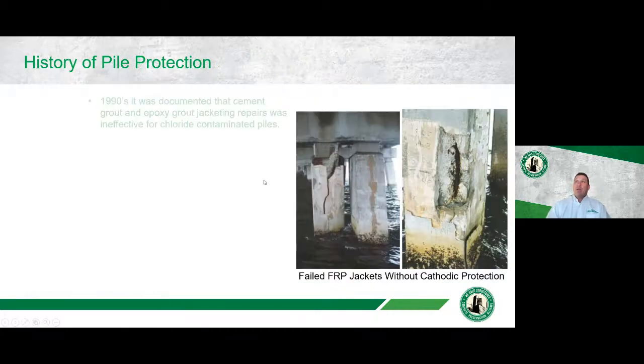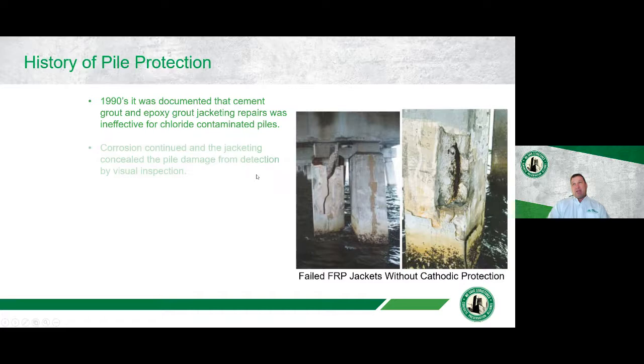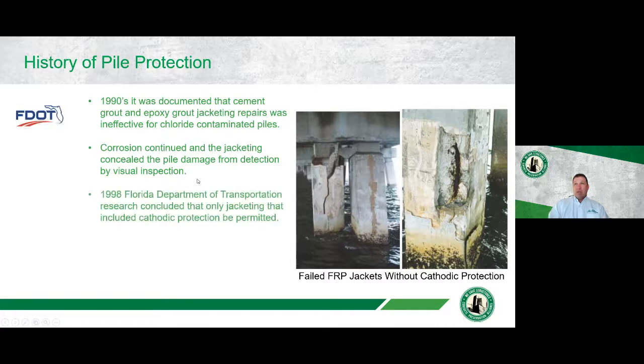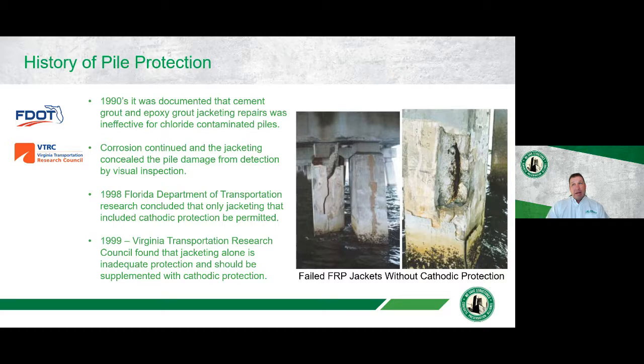So what happened was in the 90s, it was documented that these types of jacketing systems, the mass-filled concrete jackets and the epoxy-filled jackets, basically were just concealing the corrosion that was occurring underneath of these jacket systems, and they weren't controlling any of the corrosion that was actually continuing. And so in 1998, the Florida Department of Transportation, so that's the state I obviously live in here, they actually concluded that the only jacketing that was allowed within the state was jacketing that had cathodic protection incorporated into the jacket itself. Similarly, in 99, the Virginia Transportation Research Council also found during their studies a similar conclusion, and also all of their jackets had to be supplemented with some sort of cathodic protection system.